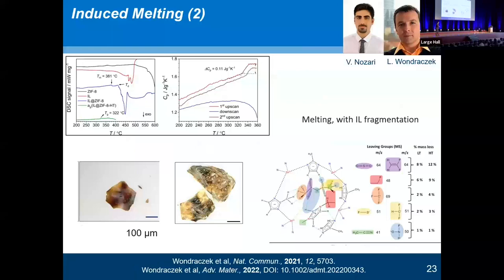But the health warning that comes with this is that you still have some of your ionic liquid inside. The system is melting because your ligand, when it's dissociated, is somehow being stabilized by your ionic liquid fragments, but the glass which is left over is very complicated to analyze indeed, as some of this MS data showed.